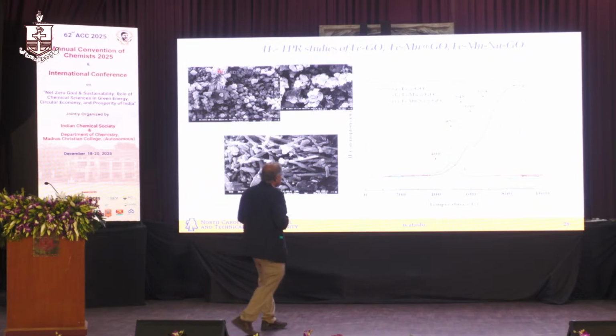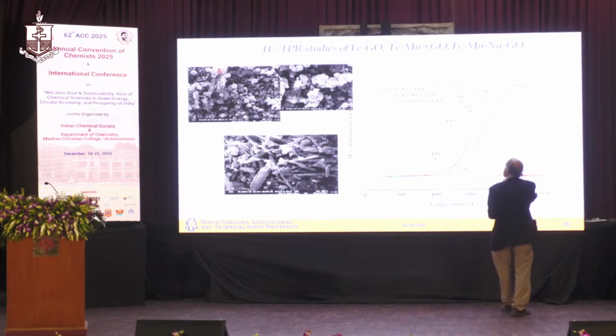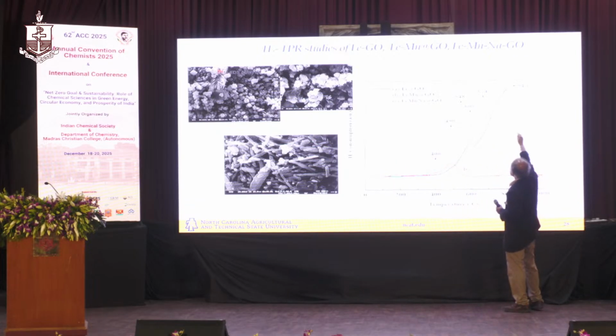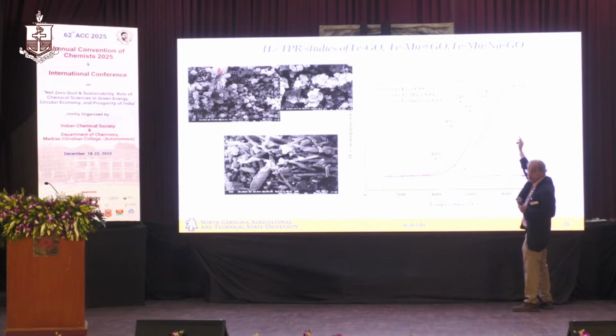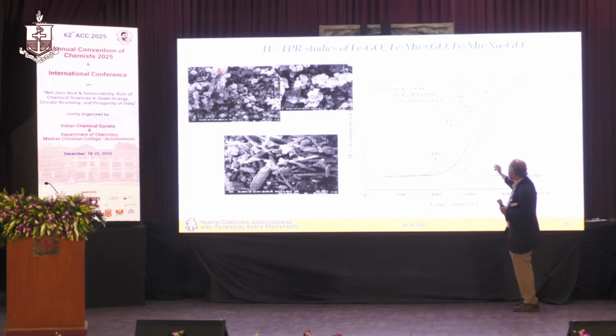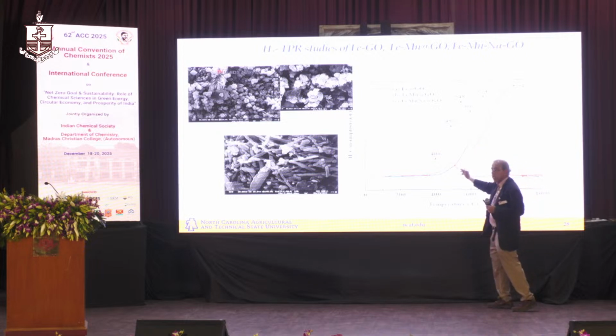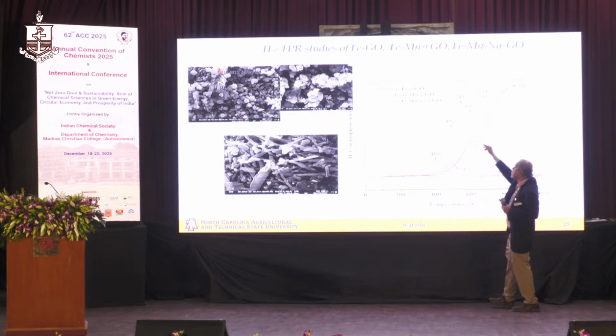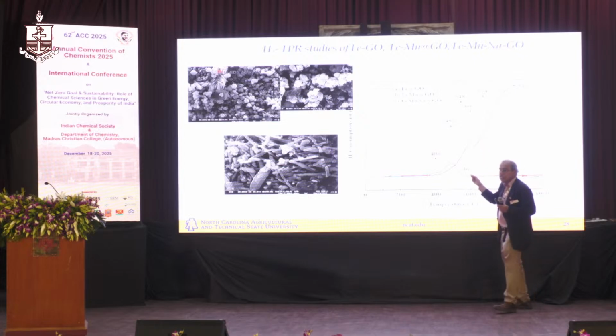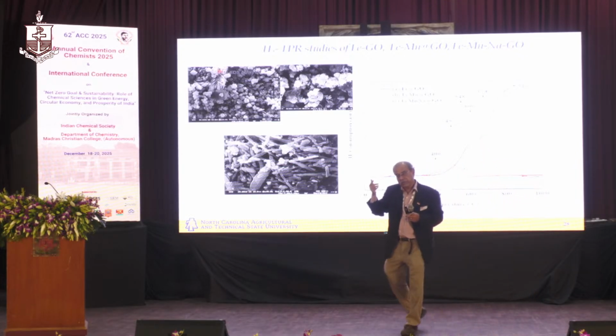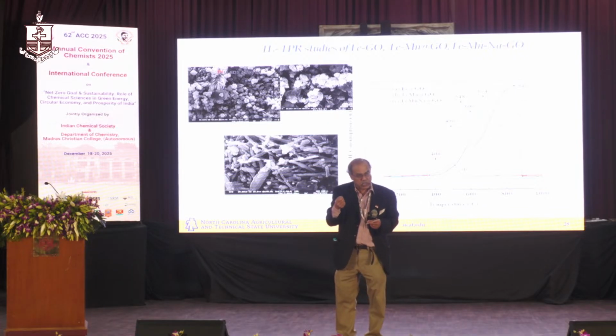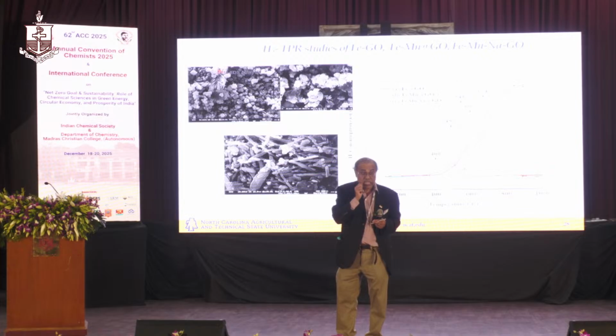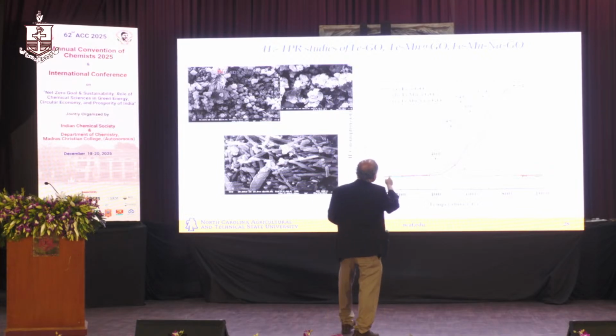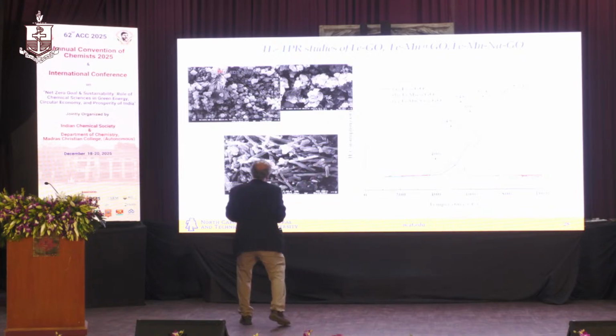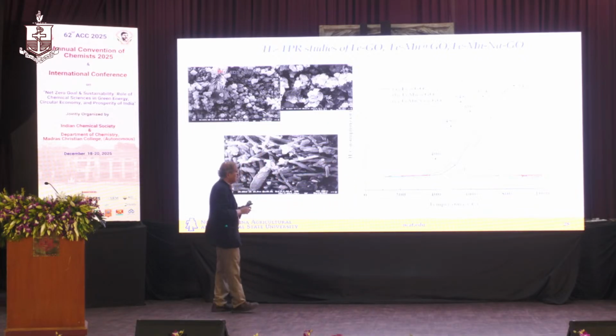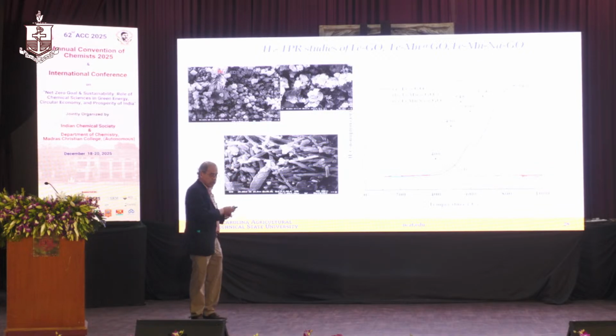Okay. So if you look at this here, you can see that for the iron graphene oxide, the black one, the temperature is 819. But the moment you have the promoter, like manganese, it moves way over here. Okay? And then if you have manganese and sodium, the blue one, you can see this. So what are these peaks? Because you have this Fe3O4, right? Which is a mixed oxide, FeO and Fe2O3, and you reduce each of those. Okay? And that is the active species for catalysis. And you see, of course, you look at the shapes, rod type, and all these kinds of things. We didn't delve into this.